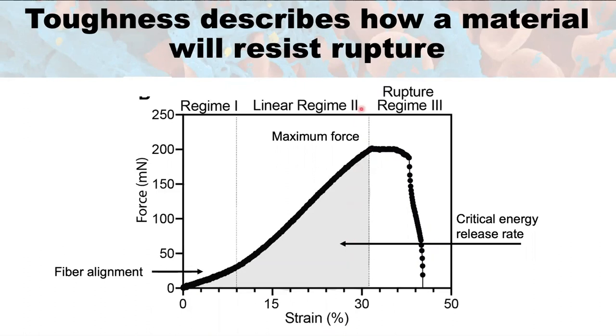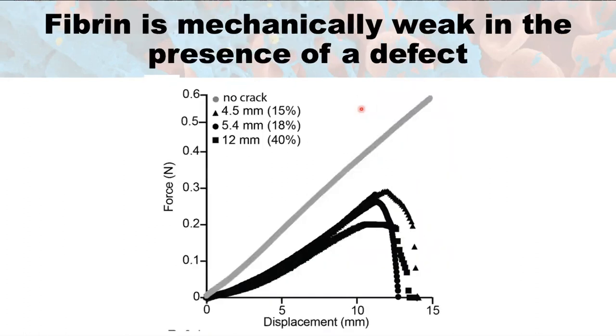And so we're able to take first this experimental data and extract this information, which was done in collaboration with John Bassani at the University of Pennsylvania. So one of the first observations that we wanted to make, and that's important to note, is that if we look at these force displacement curves in a fibrin gel that is made without any cracks or defects being inserted, you can see that the mechanical properties, which are shown in the gray curve here, are significantly stronger than the mechanical properties of the black curves, regardless of the crack length that we're putting into these curves, right? Which tells us that fibrin is mechanically weak in the presence of a defect.